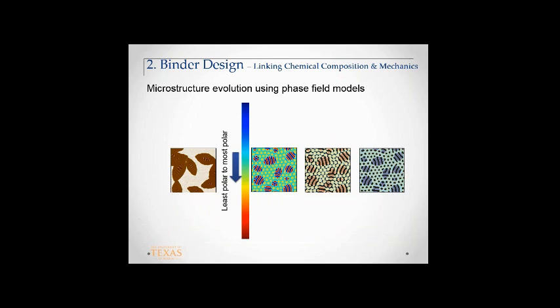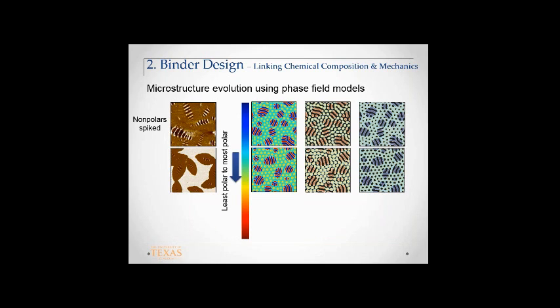And then we take a non-polar spiked fraction, and we see that these structures are now really pushing against each other and growing. We don't see that much growth here, but on average, the size of these structures is slightly increased from these. So there is some, again, what I call circumstantial evidence. It's not a smoking gun, and if I'm a lawyer using this to fight a case, it's still weak evidence. But this is the best I got so far, and I continue to work on this.